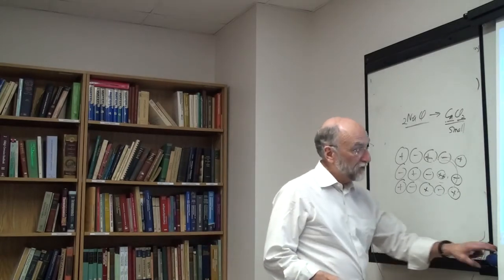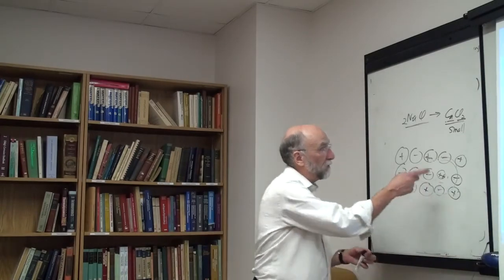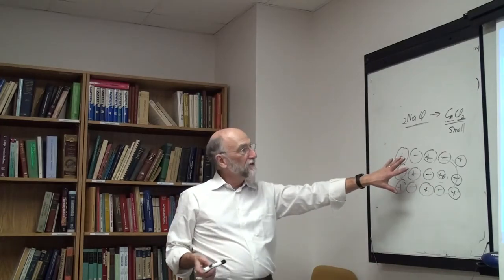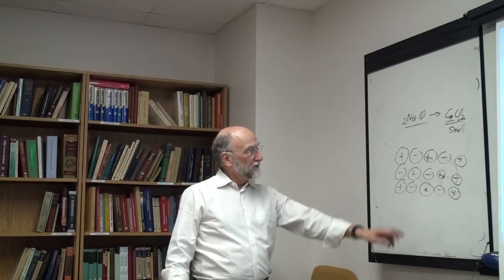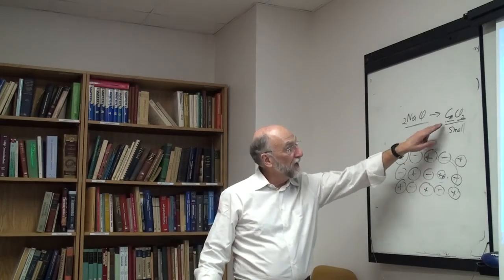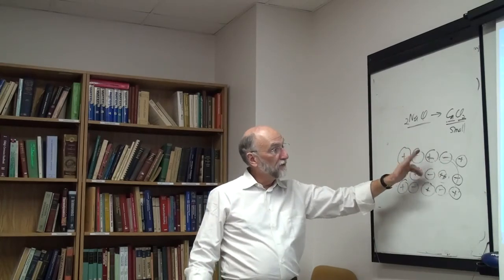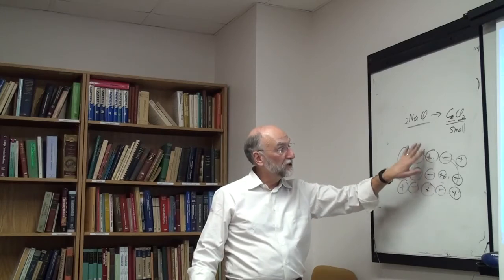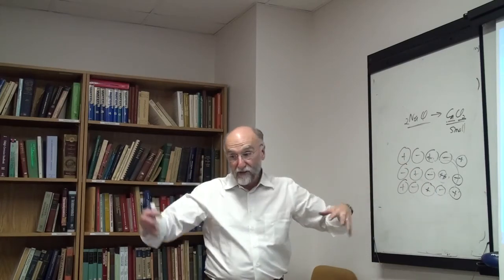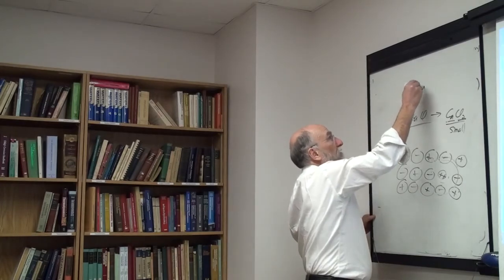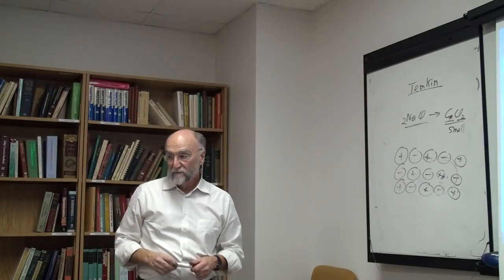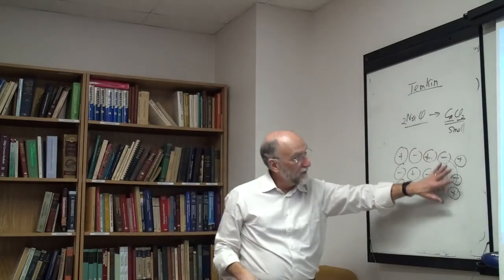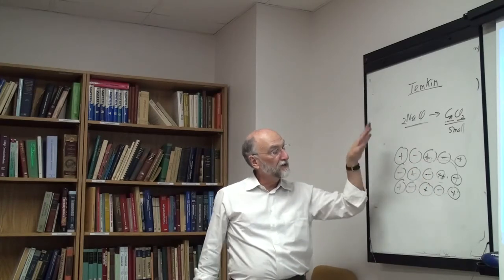Okay. So now we have to somehow take that into account. This model, by the way, in the liquid phase, says that you don't form vacancies. In other words, the calciums replace the sodiums with no regard for the charge. The doubly charged and the singly charged or triply charged ions just mix on the sublattice. The number of sublattice sites change. That's called the Temkin model, because of the Russian who in 1948 proposed it. Okay, the Temkin model is the model saying that you don't have vacancies in liquid. The cations mix on cation sites, the anions mix on anion sites, regardless of their charge.